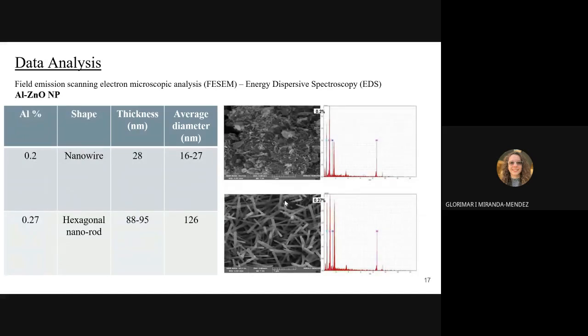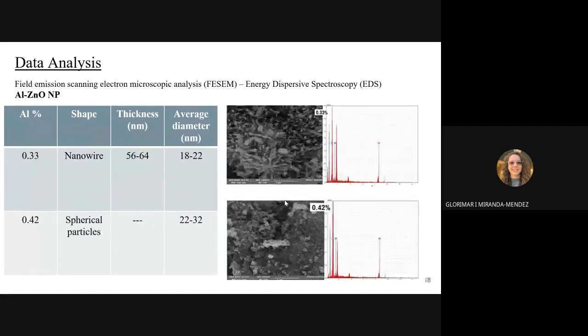In the aluminum doped zinc oxide nanoparticles, the 0.2% they determined to be nanowire shaped with an average diameter of 16 to 27. The 0.27% they determined to have a hexagonal nanorod shape with an average diameter of 126. And the 0.33 also has a nanowire shape with 18 to 22 diameter. And the 0.42% they obtain spherical shaped particles with 22 to 32 average diameters.